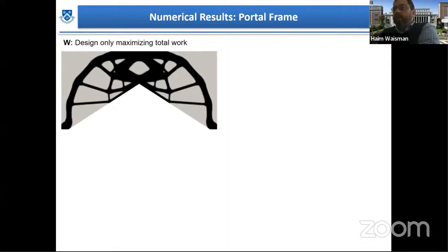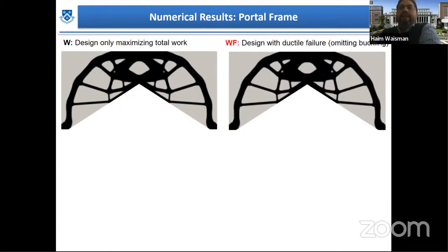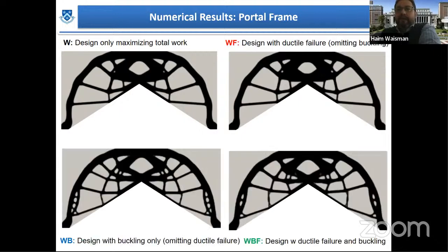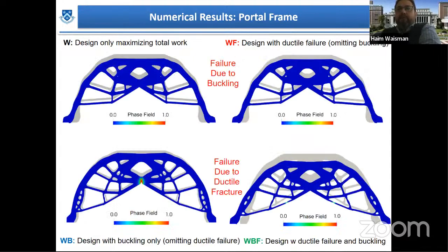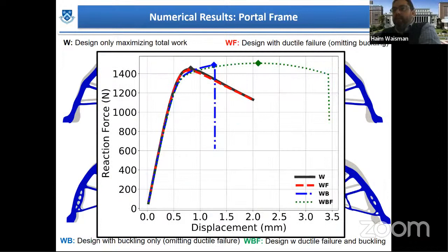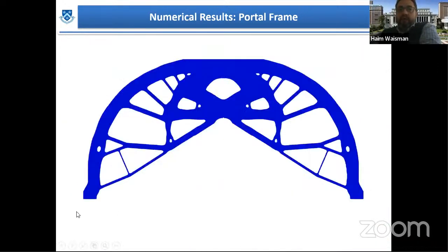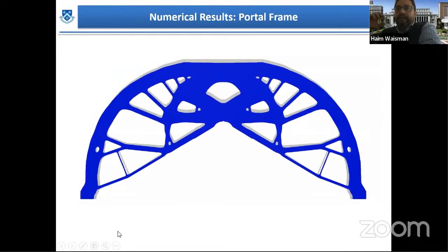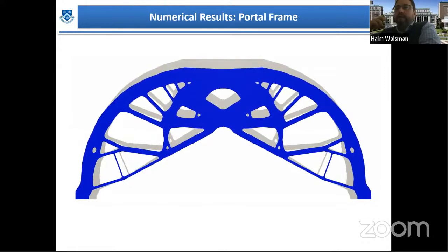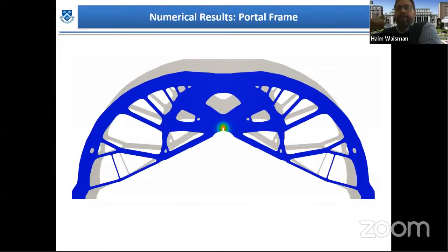Another example is this portal frame example. Again, we have one or two minutes left. Yes, so I'm fast. I have the same design for the portal frame. I have the four different designs. And again, these are the results, failure due to buckling, failure due to fracture. Again, we see the same force displacement curves where we increase the peak load by almost 5% and the total work by 270%. And then finally, I just wanted to show this movie that shows how we take a candidate design and subject it to a large phase field ductile fracture to test it. You can see the fracture initiated and propagates essentially as a mode 1 fracture.